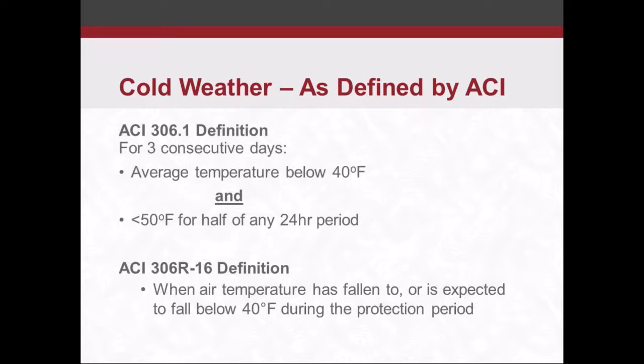ACI 306, which is the guide to cold weather concreting, defines cold weather as whenever the air temperature has fallen to or is expected to fall below 40 degrees during the protection period. 40 degrees is kind of a set number because below 40 degrees, cement hydration slows down significantly. Obviously at 32 degrees, when water freezes, it stops altogether. But right around 34, 35, 36 degrees is when it really slows down almost to nothing. Depending on some other factors, between say 35 and 40 degrees, we're getting very little cement hydration. So that's the reason for the 40 degree cutoff.